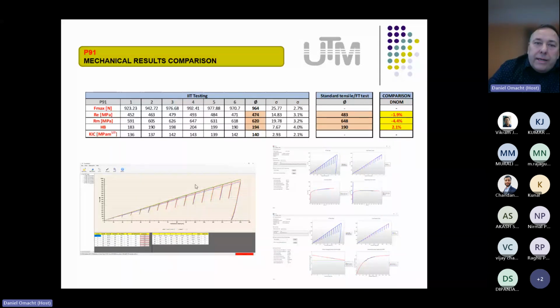And in this picture, you can see 3 tables. In the first table, you can see 6 tests, as is visible here in this chart, and the evaluation of these tests as an average value. In the second table, you can see the average value which was obtained by standard tensile tests, 3 tensile tests, average value, and comparison. And you can see that for yield strength, it's about 1.9%. For ultimate tensile strength, the deviation is 4%, and for the hardness test it is 2%.